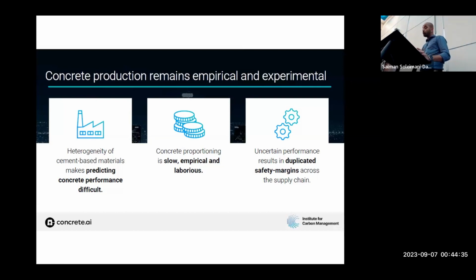And the reason that this comes about is I'm a third generation civil engineer. So I spent my childhood listening to people talk about building very large objects, right? And I heard my father talk about this all the time. Oh, you know what? We ordered an M20 concrete and what we got was an M10. We ordered an M30 and we got an M20. On the other hand, sometimes you order an M20 and you get an M50, right? And you really never know. What the M tells you is the compressive strength in megapascals, so M10 is 10 megapascal, or M50 is 50 megapascal.